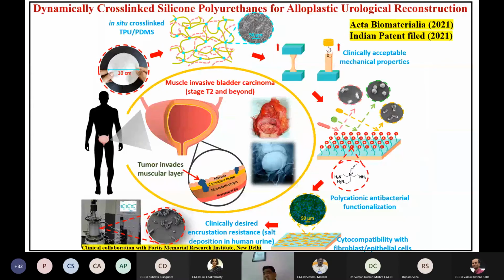Now, this kind of very wide range of property requirements cannot be met by a single material. So we have developed in situ cross-linked thermoplastic urethane polydimethylsiloxane, TPU-PDMS blends. These blends have clinically acceptable mechanical properties in terms of elastic stiffness, which is fairly close to that of the natural tissues, and also suture strength. Suture strength is very important.